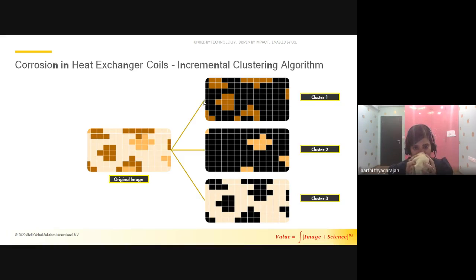The drawback of this method is the need for prior knowledge of the number of clusters, and we do have SEC images where we have more than 4 or 5 regions, or the number of clusters is different. Therefore, we came up with an approach called the incremental clustering algorithm. It's a more general technique to segment images, and it adopts a version of the k-means method, and it was quite successful in thin sections of rocks, but we realized that we could also use this for these SEC images. And what it broadly does is pre-processing, feature extraction, clustering, and corrections.